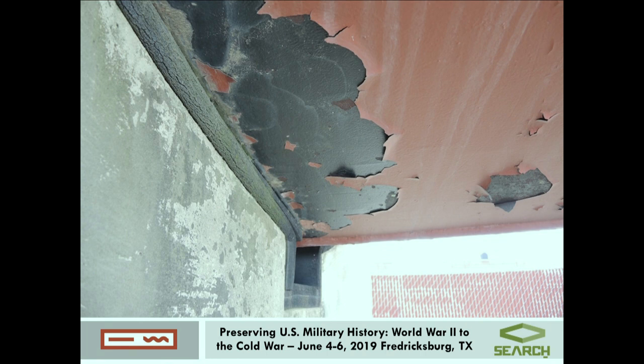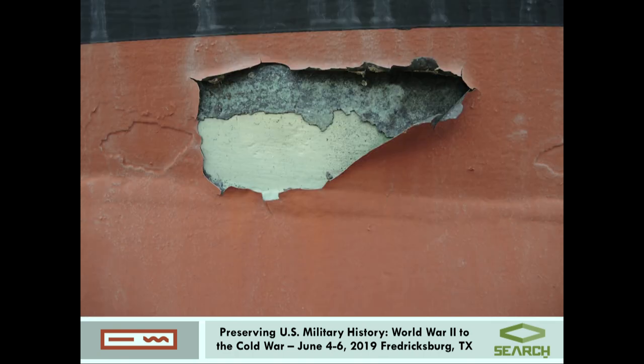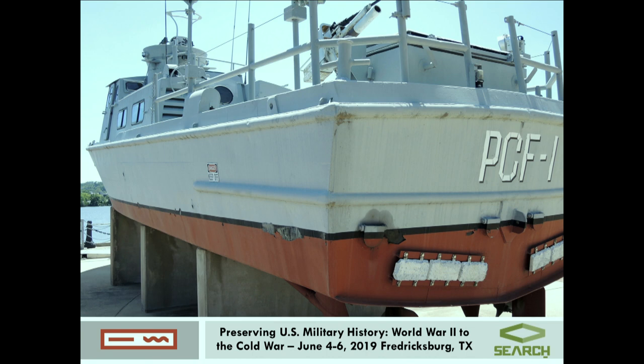The coating, which we don't know if the coating that we had seen in 2014 was original or not, but what we could say is that the coating was failing in numerous areas, and the epoxy was blanching and failing in areas where the hull was really corroded, particularly near the bilge of the boat. You can see the clear separation between the layers, and so it was very typical of that boat to see those localized failures all around.